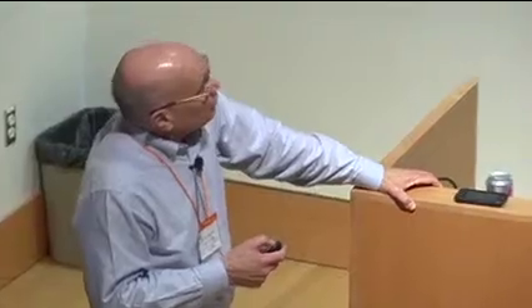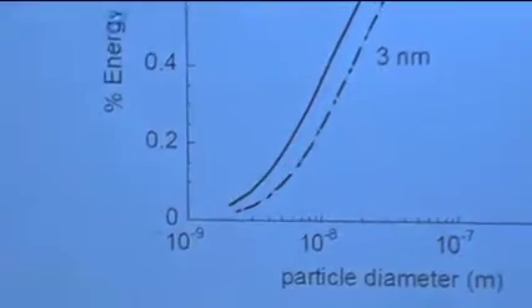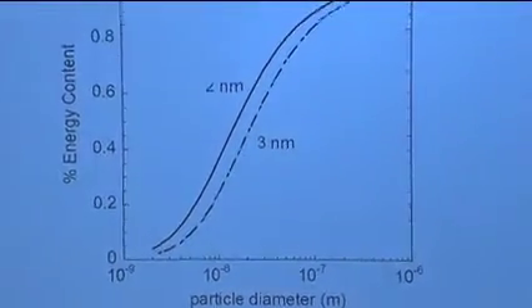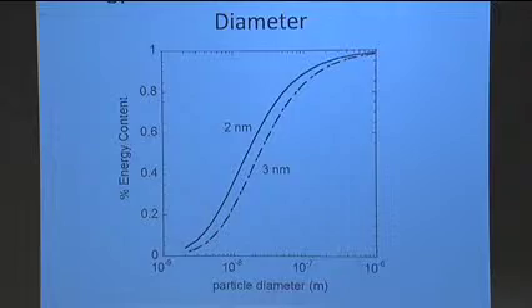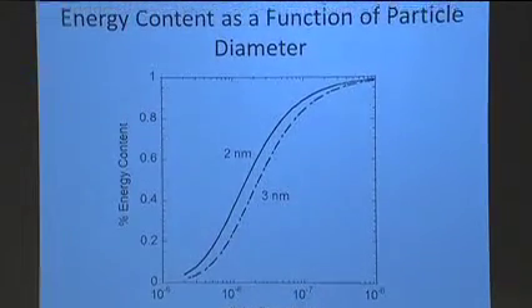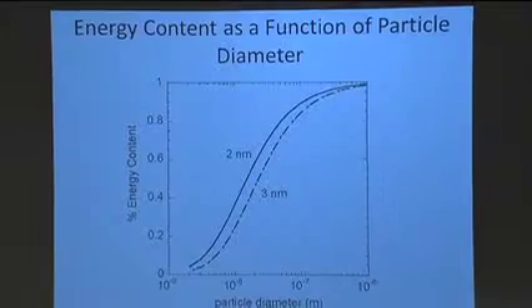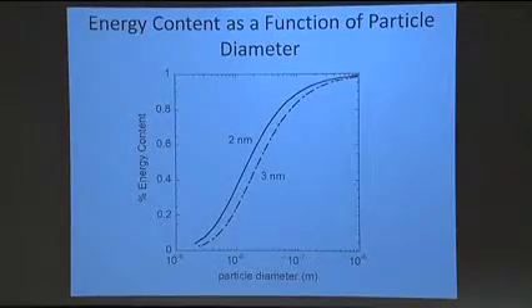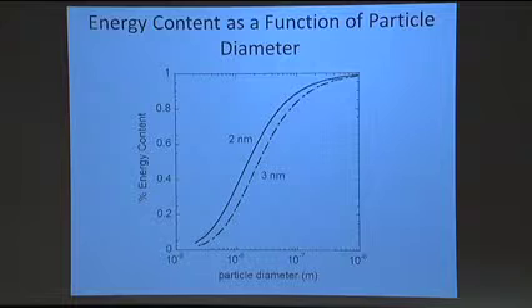And as I shrink the particle down, the thickness of this oxide layer does not change. So what that means is, as I go down to the nanometer scale, more and more of the particle is really an oxide. If I'm looking at the core aluminum as my fuel, and I shrink these naturally occurring particles to the nanometer scale, I would find that I'm losing a significant amount of energy content in the particle. And that's why I come back to passivation, and the capping and the coatings are going to become very important to manipulate, not only to control the material, but also to make them more reactive in themselves.